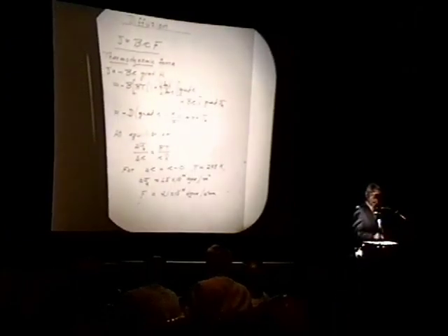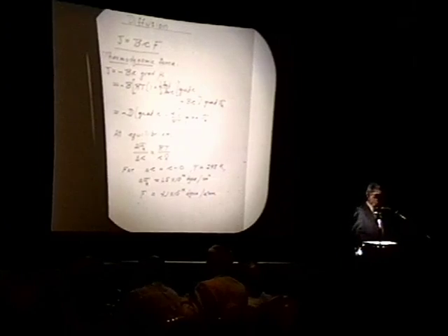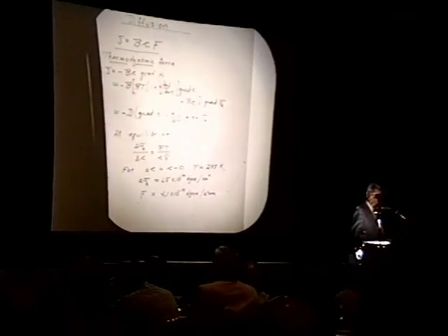Times the partial volume of the interstitial species. So that can be written in this fashion, where now I combine the mobility with the Einstein relationship to form the diffusivity. And that already includes the thermodynamic term.